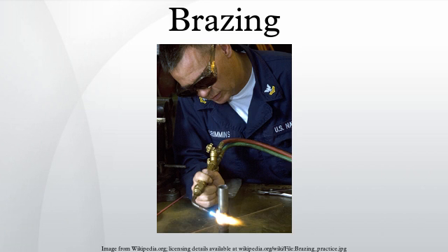Fundamentals: in order to obtain high-quality brazed joints, parts must be closely fitted, and the base metals must be exceptionally clean and free of oxides. In most cases, joint clearances of 0.03 to 0.08 mm are recommended for the best capillary action and joint strength. However, in some brazing operations it is not uncommon to have joint clearances around 0.6 mm.